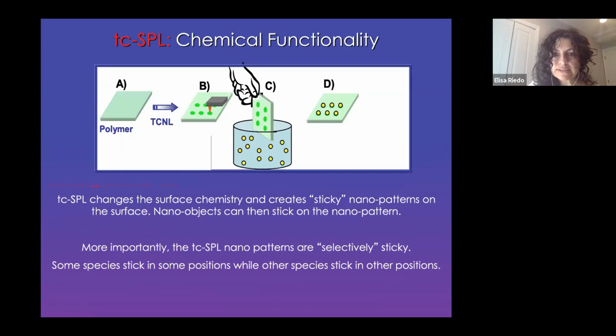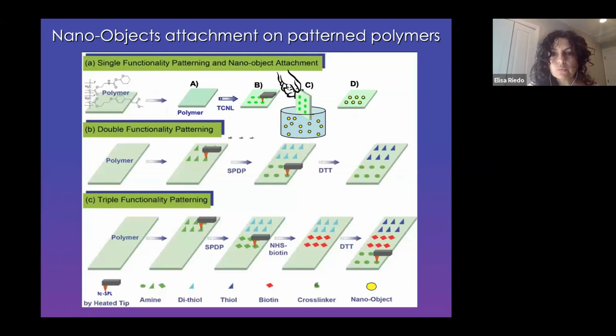So the next step was, okay, can we actually think about creating patterns of carboxylic acid groups or even of amine groups, which are actually perfect functional groups to attach biomolecules, and then dip in the solution of the biomolecule of interest, say proteins, and use some bioconjugation scheme to attach the biomolecules selectively to the patterns of amine, then some wash protocol, and generate a pattern of proteins, for example. So that was the idea. This is the second type of copolymer.